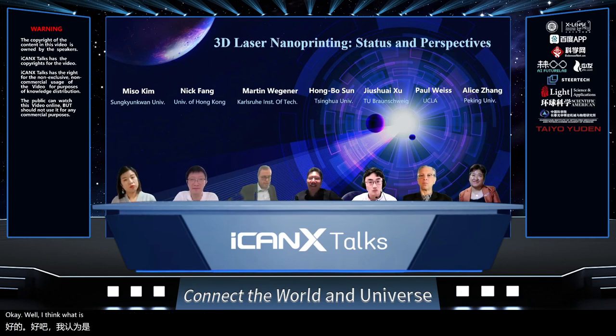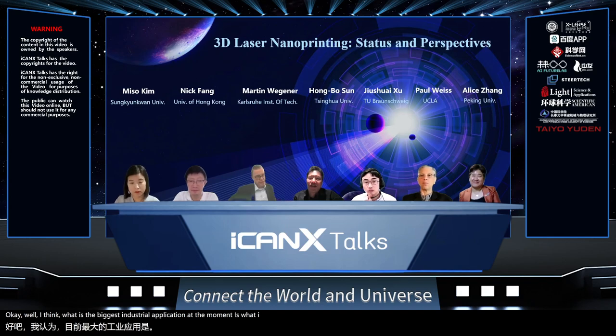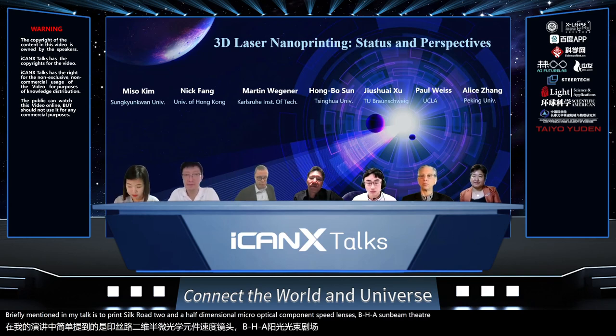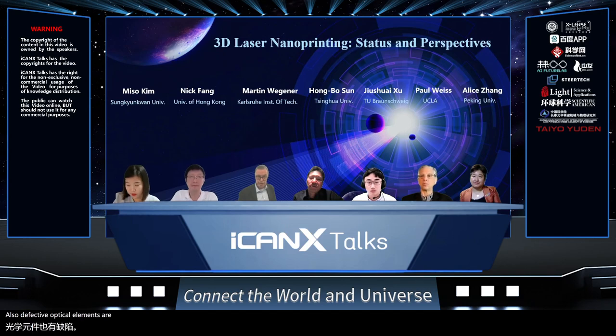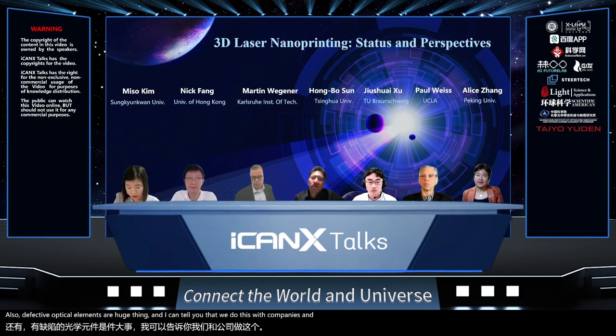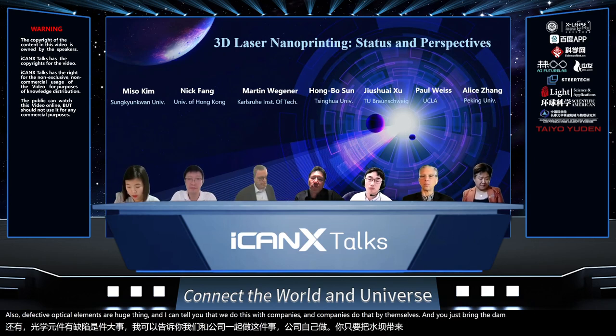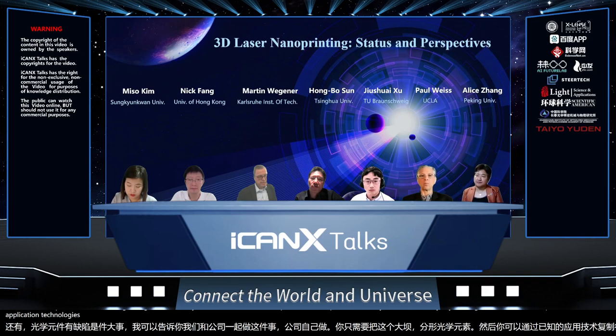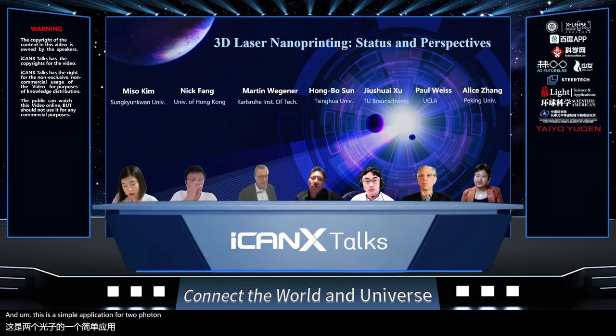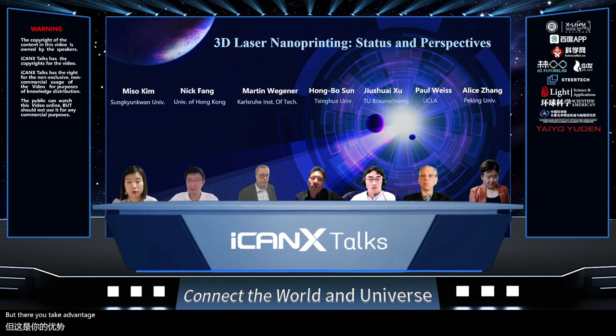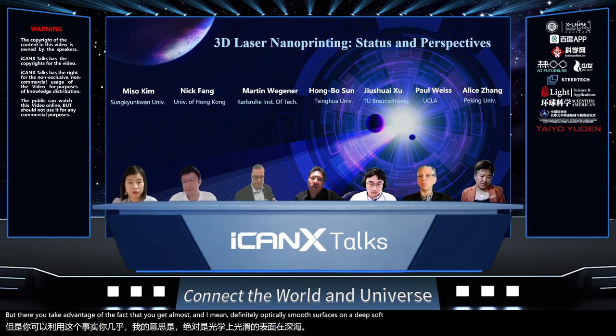Okay. Well, I think the biggest industrial application at the moment is what I briefly mentioned in my talk: to print so-called 2.5-dimensional micro-optical components, be it lenses or some beam steering unit. Also, diffractive optical elements are a huge thing. We do this with companies, and companies do that by themselves. You just print the diffractive optical element, and then you replicate it as many times as you want by known replication technologies. This is a simple application for two-photon printing, because it's not a truly three-dimensional structure. It doesn't have undercuts. But there, you take advantage of the fact that you get optically smooth surfaces.